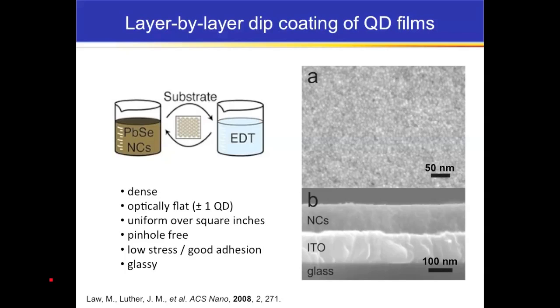We then dip that into our ligand treatment solution, in this case ethane dithiol. That strips off the oleate and allows the dots to move closer together. It also insolubilizes the dots, and so you can then just repeat this process over and over, and build up a thin film of whatever thickness you would like. The nice thing is that the films are very high quality. They're dense. They don't have pinholes. They're very flat, and so forth. This is a top-down view and then a cross-sectional view on a piece of ITO.